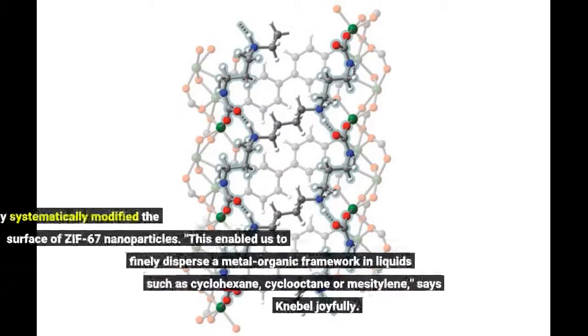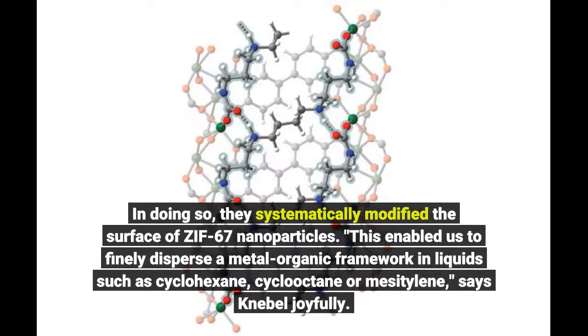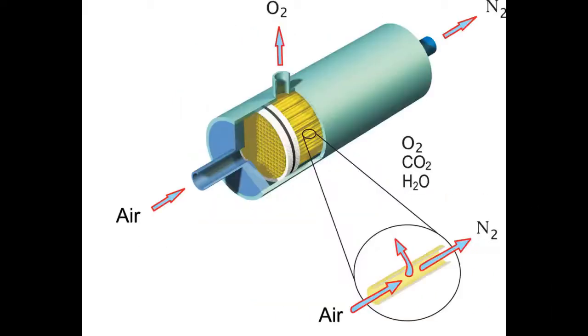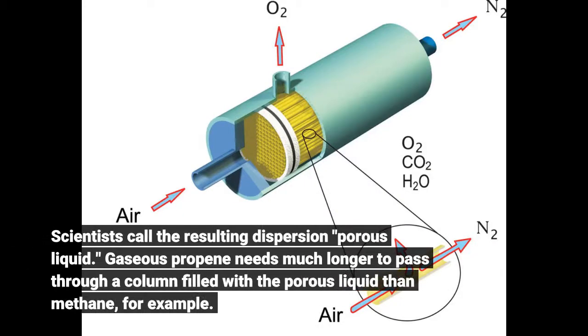In doing so, they systematically modified the surface of ZIF-67 nanoparticles. This enabled us to finely disperse a metal organic framework in liquids such as cyclohexane, cyclooctane or mesitylene, says Knebel joyfully. Scientists call the resulting dispersion porous liquid.